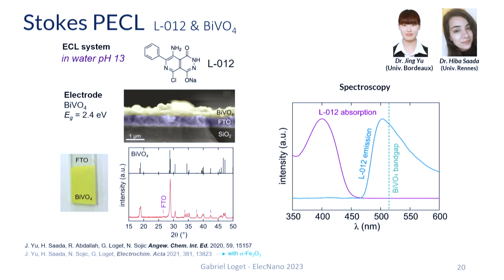So what about now the photoanodes? We are not working anymore with silicon, so we wanted to use a semiconductor with a broader band gap. We used bismuth vanadate, which is an N-type material widely used for water splitting. We deposited our bismuth vanadate layer on transparent conductive oxide, FTO-coated silicon oxide. You see that this semiconductor has a characteristic very yellow color. And here is now the band gap of bismuth vanadate, which is at much lower wavelengths than silicon.